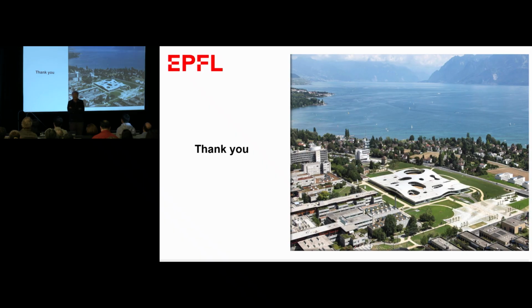I haven't cited the work of some of our colleagues. We are now running the so-called ISOS-L3 test at 85 degrees. That is 85 degrees centigrade on the cell all the time, and then we have full sunlight on it, and then we have maximum power point, which means electrical stress across the cell. And some people now get 2,000 hours. Imagine you're in a sauna at 85 degrees for 2,000 hours, and they lose very little, just a few percentage points.